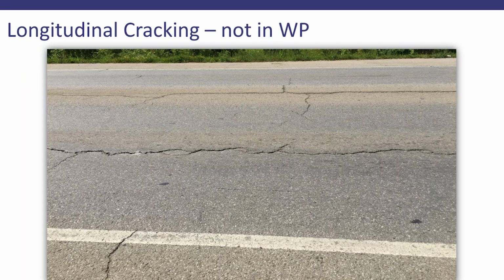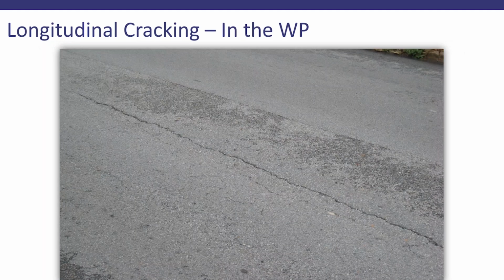Okay, so in this picture, you can see some longitudinal cracking. Those cracks are not in the wheel path. We've got them showing up at the longitudinal joint and then about halfway, like right in the middle of the lane. This one, on the other hand, is right where the traffic goes. So you can see, if you can see my cursor, right along here is the actual longitudinal joint. And then offset a little bit, we've got this longitudinal crack. This one's actually really nice and straight, but it is in the wheel path, which is going to indicate a load-related failure.